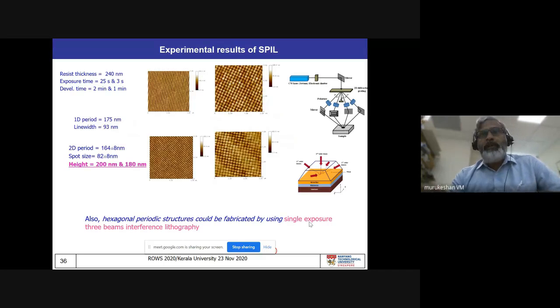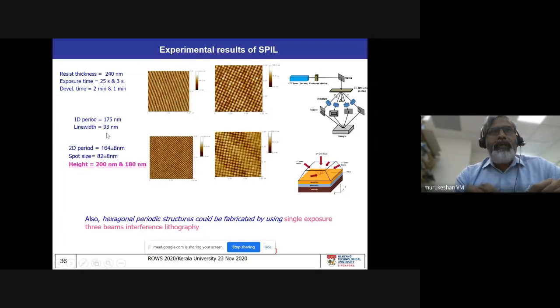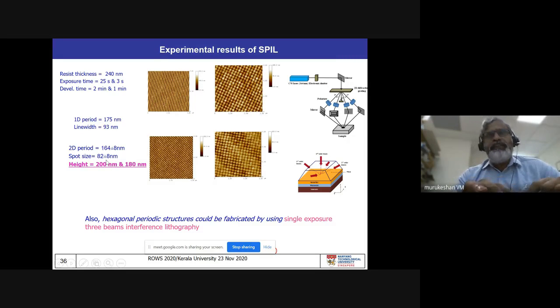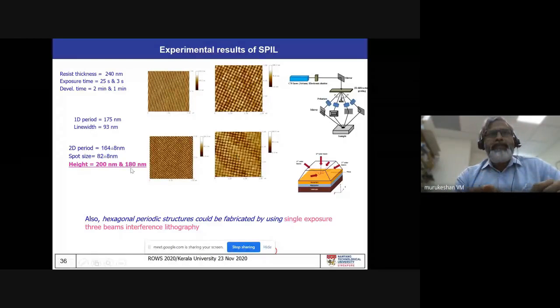And that is what is shown here, that you can get a line width of, if it is 2 beams, straight line patterns of about 90 nanometers. Or if you are using 4 beams, you are able to get about the same amount, 80 to 90 nanometer feature size for the contact pillars. This is the top view, and the height is about 200 nanometers.